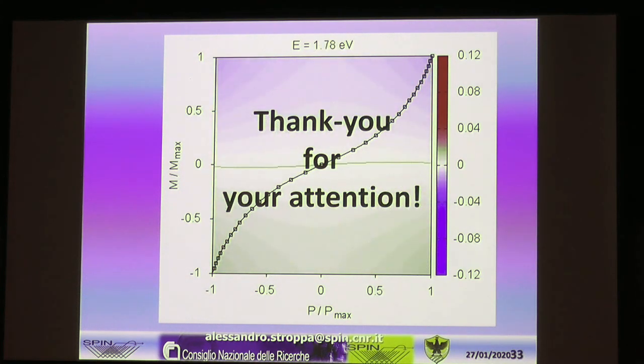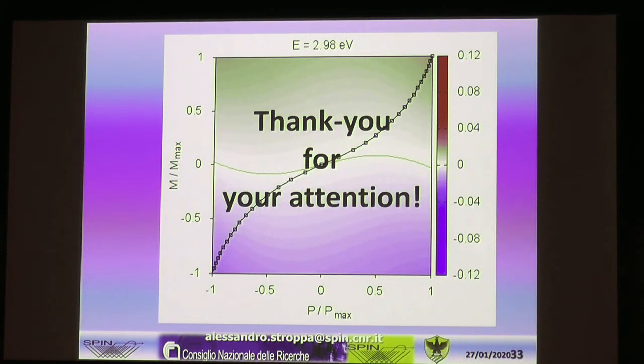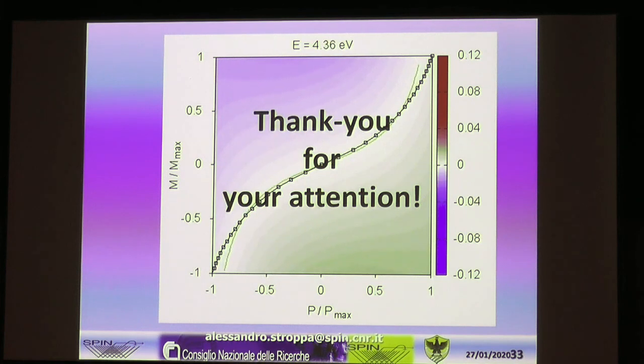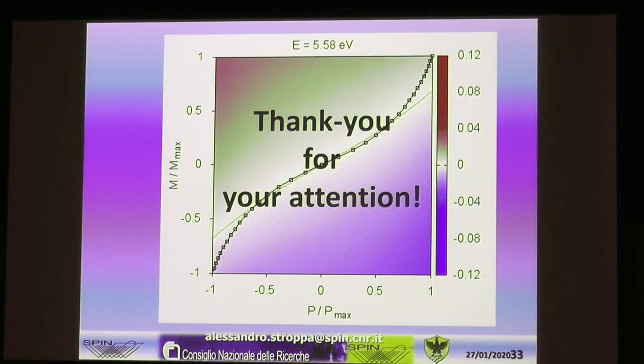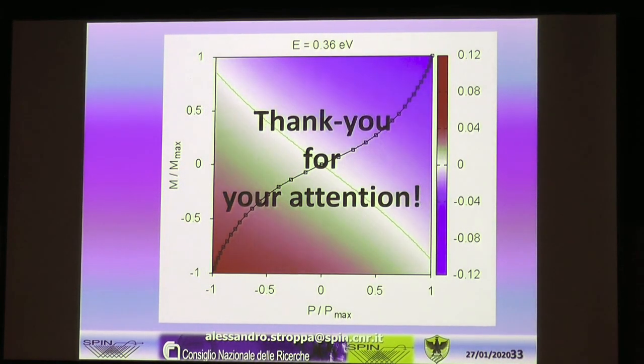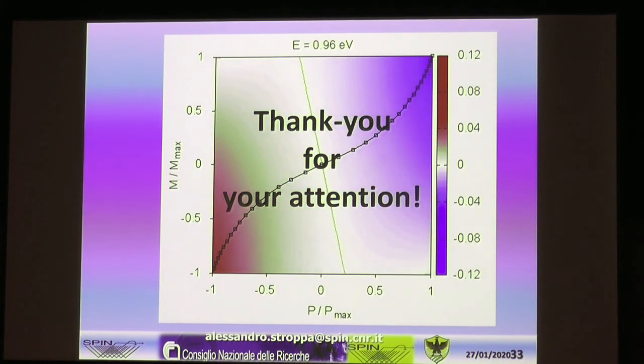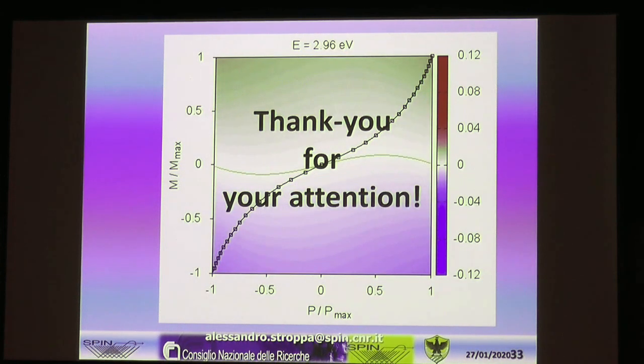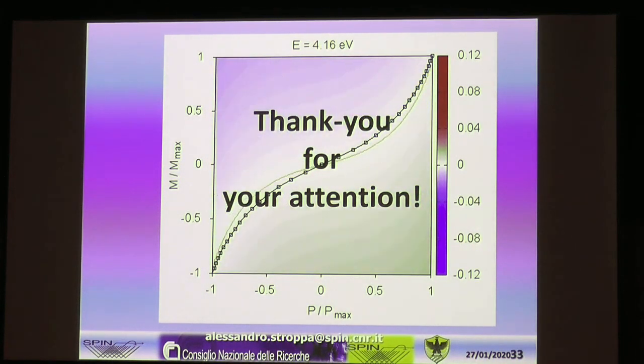Q: You said copper is the only one that's ferroelectric in that series — are there other choices of the organic part that give ferroelectricity? A: In this case we keep the guanidinium cation and change copper to Cr²⁺, and we again have ferroelectricity. The main role is played by the Jahn-Teller ion, which introduces a distortion correlated with the organic cation. If we use another metal atom without any Jahn-Teller distortion, we get a centrosymmetric phase.